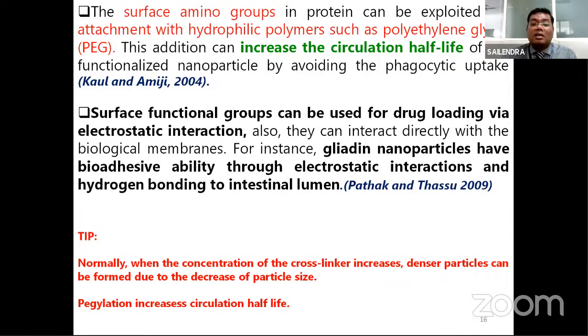Now, you want to avoid the phagocytic machinery present within the body, which is going to degrade your nanoparticle. Functionalize it with a polyethylene glycol coating, or a polyethylene glycol layer, and you will be avoiding this phagocytic uptake and degradation of the nanoparticle. Even more, the surface functional groups can be used for drug loading by electrostatic interaction.